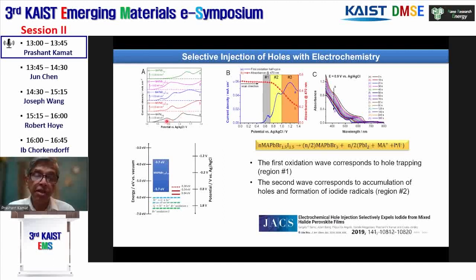We also did electrochemistry. Again, these are the cyclic voltammograms, and you can see here with increasing bromide, the peak shifts to more positive potential because bromide is more difficult to oxidize than iodide, and mixed halides are somewhere in between. And we also tested first in DCM. It is stable for 3 to 4 hours. And here is the region where we probe.